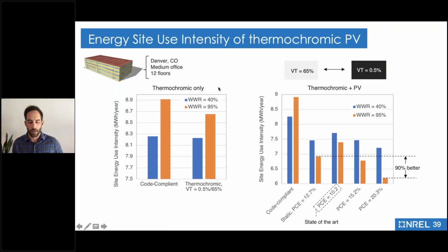So let's go back to that building energy model. And this is one of the last slides I'll show with any kind of data on it. This is, again, looking at that same Denver medium office building with 12 floors using EnergyPlus simulation on the Amazon server. We're looking at site energy use intensity as a function of what type of IGU you put on that medium office building. And now we have, again, 2 window-to-wall ratios. On the left side of your screen, we have the code compliance. So this is the low-E double glazed window versus what happens if you take that switching phenomenon I just showed you, turn off the photovoltaics and only look at what happens if you have a thermochromic window. You get some performance enhancement. It's not dramatic, but it does improve your energy efficiency, especially when you have a highly glazed building like a window-to-wall ratio of 95%.